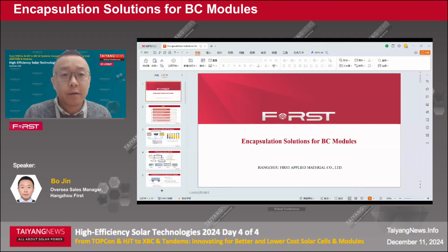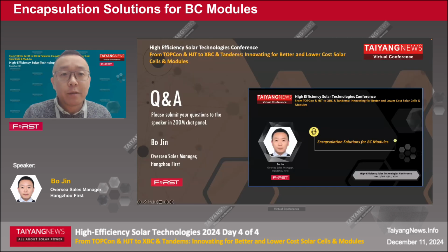As for the EPE material, the grammage of the POE layer in the middle is 110 grammage. This is currently what we consider the limit to keep the anti-PID property. And of course, based on cell technology development, we could continue our exploration and tests to make it thinner and thinner.